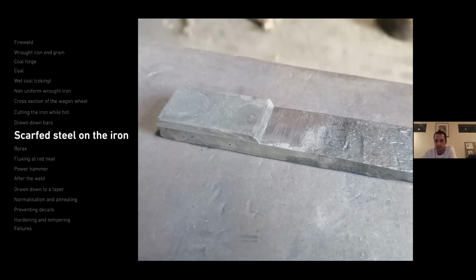Iron and steel have got very different properties in that the carbon in the steel affects the welding temperature. So high carbon steel has got a much lower welding temperature than the iron. The iron is welded at almost white heat, while the carbon steel is sort of a bright orange, almost yellow. And to get the dissimilar materials to a uniform heat that they actually stick is the trick.